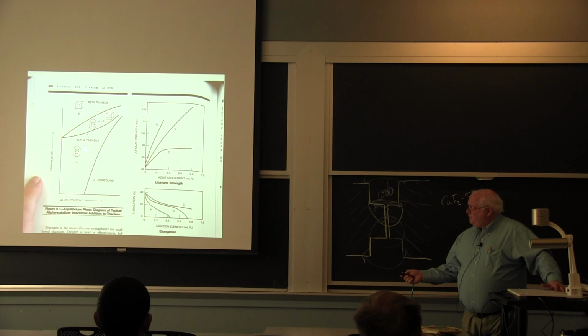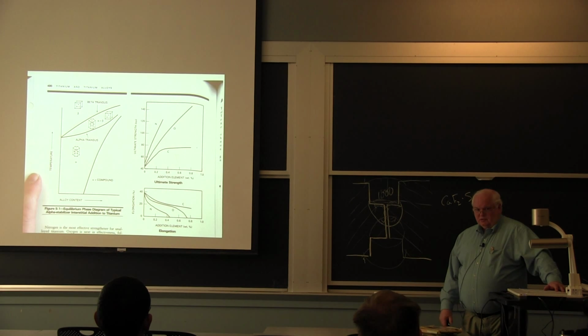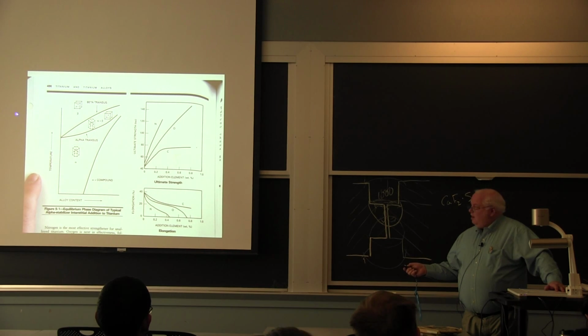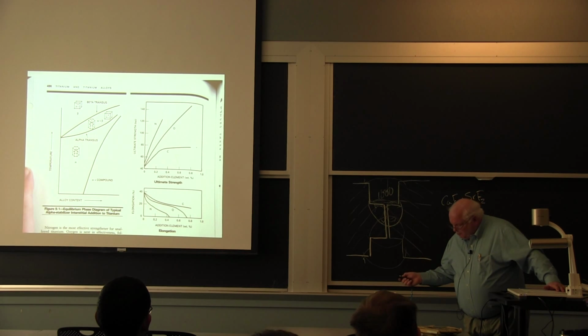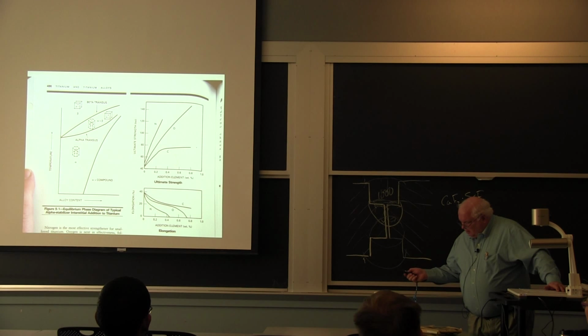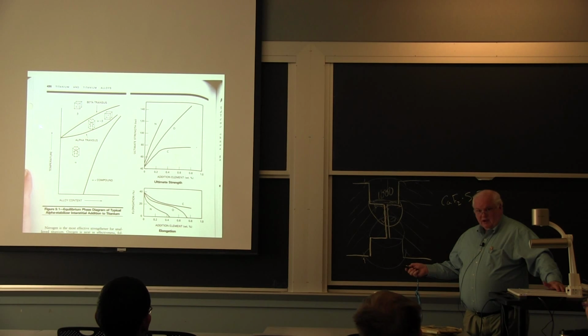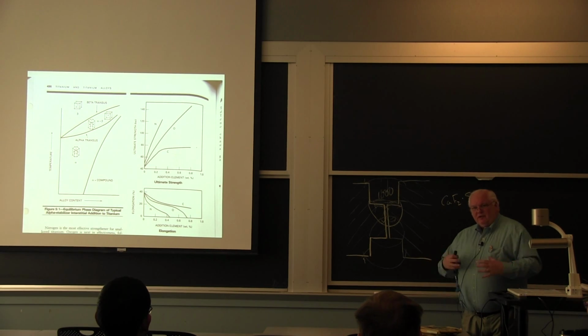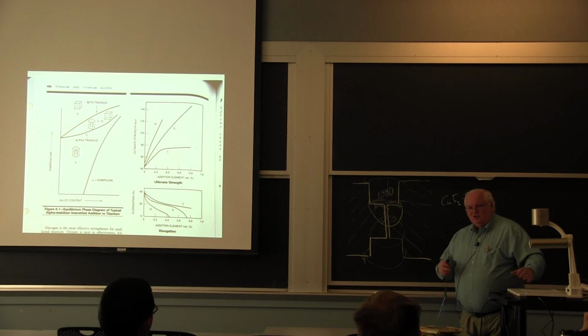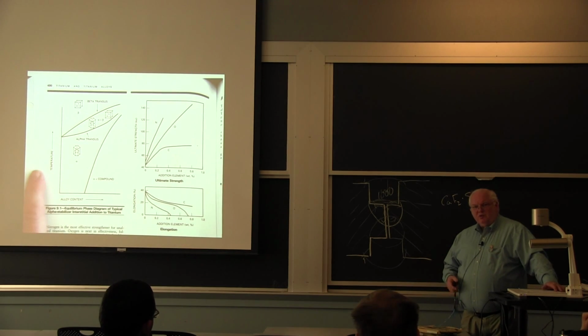No, the thermal expansion is about the same in both the crystal structures. It's anisotropic here. It's not the same in both directions. But in fact, this temperature, what is that temperature? That temperature is about 900 centigrade. Everything's plastic enough at those temperatures that you don't run. They sort of have a little bit of micro strain to accommodate each other.